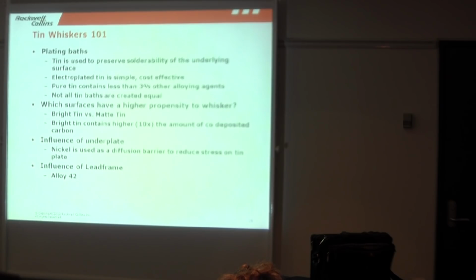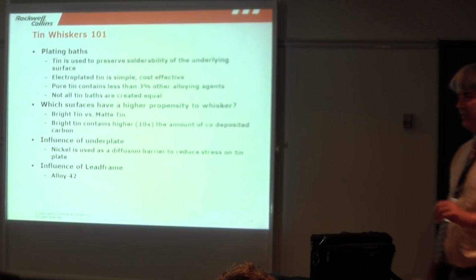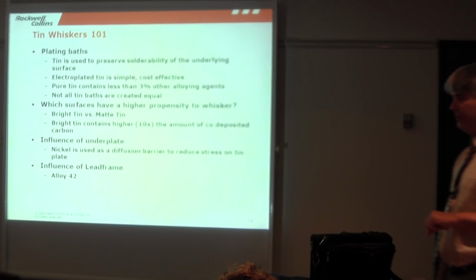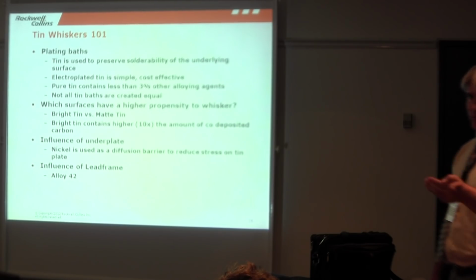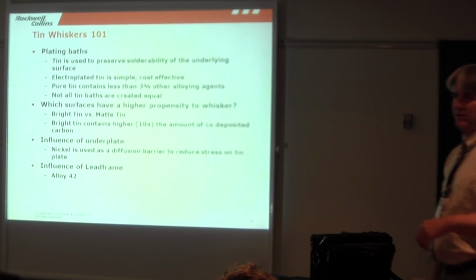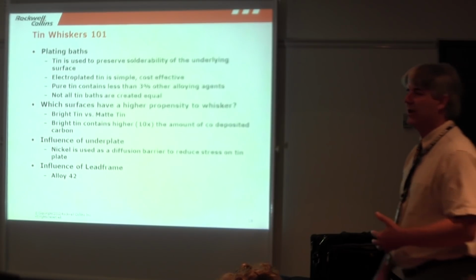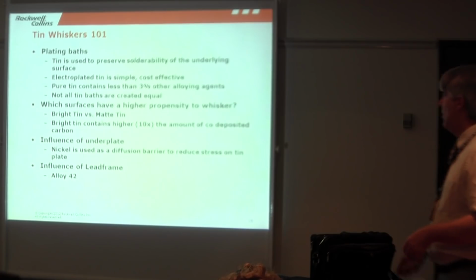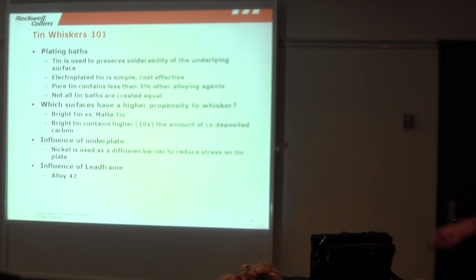A couple things that are industry consensus. Bright tin and matte tin. You'll never see a clean definition. The GEIA standard 0005-2 used to try to have a definition of what was bright and what was matte, took it out. There's just no standard. Nobody in the industry can agree on it. But we do know that bright tin whiskers like Chia Pet. So if you don't want whiskers, make sure you're not using bright tin.